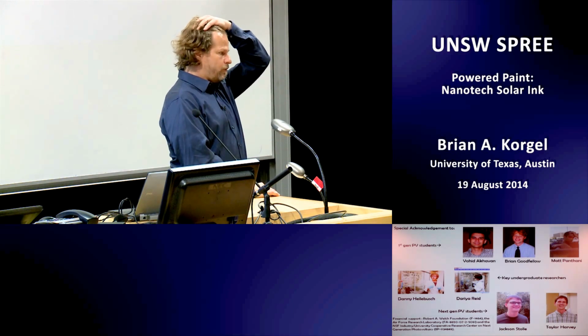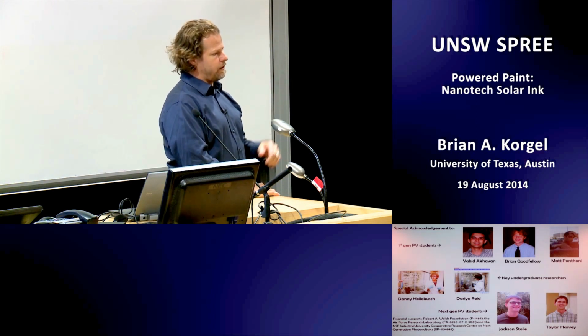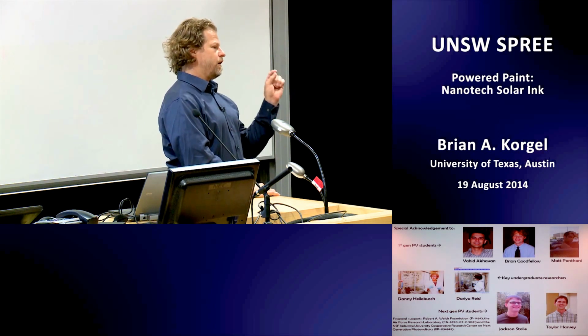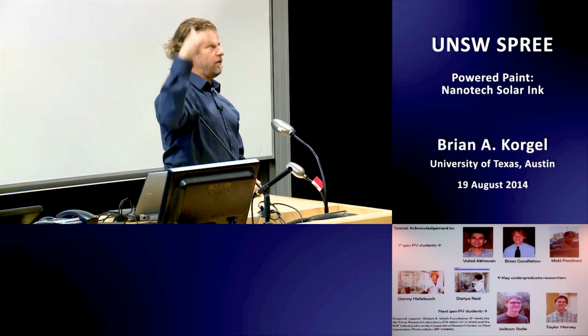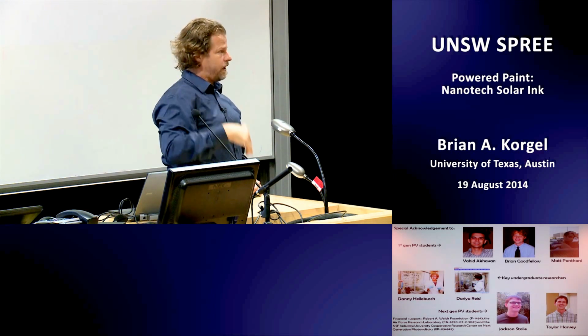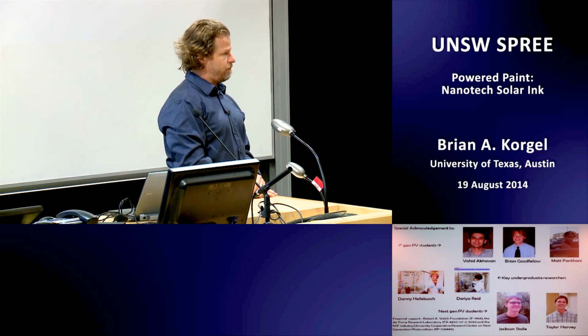I had a student in Melbourne for two months, and he was doing some measurements looking at the electron affinity of copper-indium selenide as a function of capping ligand. I haven't seen the data yet, but he said if you go from an amine to a thiol, the electron affinity can vary by as much as 0.4 volts, which is similar to lead sulfide. In lead sulfide, they've seen electron affinities vary by up to a volt by going from amines to thiols to halides. That's somewhat surprising, and I think people are learning that that's a role these ligands can play.